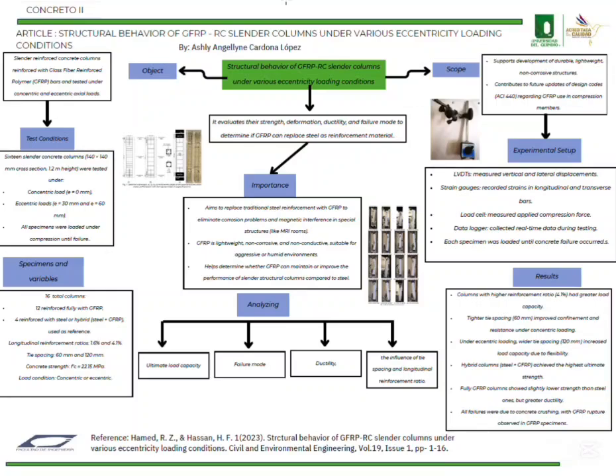When comparing reinforcement ratios, increasing the ratio significantly increased the ultimate load of the columns. The tie spacing also had a noticeable influence. Under concentric loading, tighter spacing, 60 millimeters, improved confinement and strength, but under eccentric loading, wider spacing produced better load performance because it allowed more flexibility and prevented premature cracking. Finally, when analyzing the ductility, the ability of the column to deform before failure, it was found that GFRP reinforced columns were more deformable than the steel ones, which is a positive aspect for seismic design.